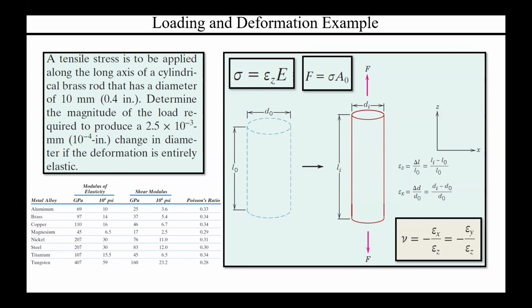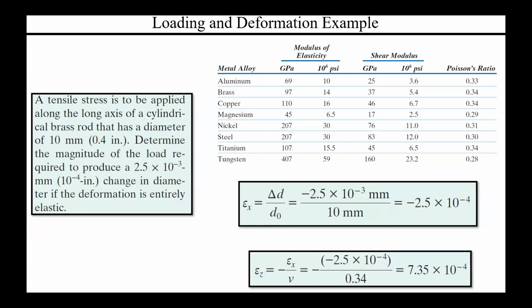There's an example problem here that you can solve. You have a tensile stress being applied to a cylindrical brass rod, and what you want is the magnitude of the load required to produce a given change in the diameter. If you know the deformation is entirely elastic, you have all your terms, so feel free to solve this on your own and then skip ahead. The first step is to recognize that what you really want is the strain in Z, since this is a tensile force being applied along that direction, and you don't have that. What you do have is a change in X, which is your cross-section diameter difference. So you can solve for that and then use Poisson's ratio, because you know it for brass, in order to solve for the strain in the Z direction.